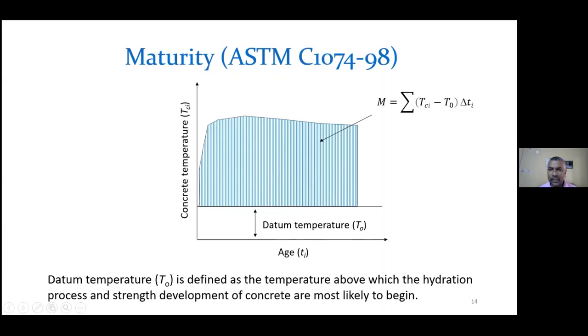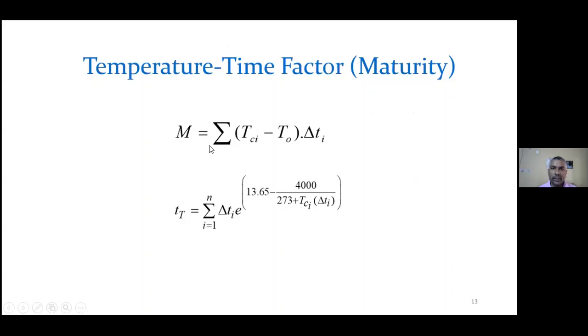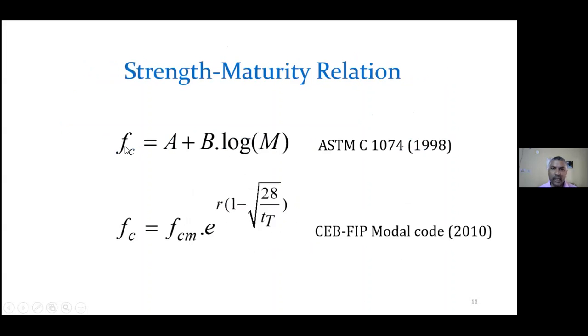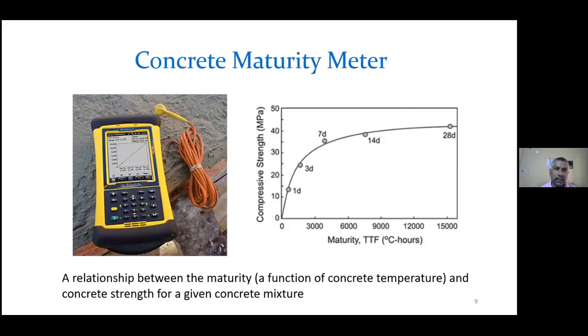As the time progresses, our maturity will be increasing. So if I know the maturity, I will put this maturity in this equation, and I will know the strength of the concrete at that particular time. Again, as the time goes, your maturity will increase, and my strength also will increase. So how the strength is gaining over time in the early age, we can predict. Similarly, we can do this using this method also. We are not developing these methods; these are already existing since 1998, so for more than 20 years these methods are available. And based on this maturity method, a maturity meter works.